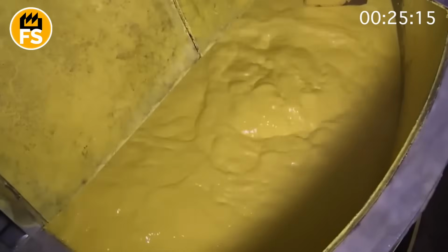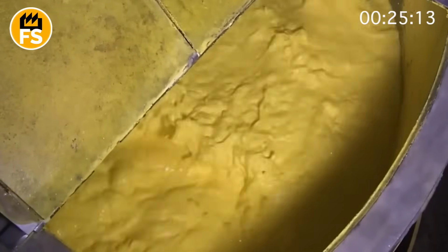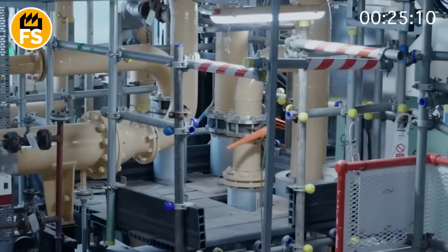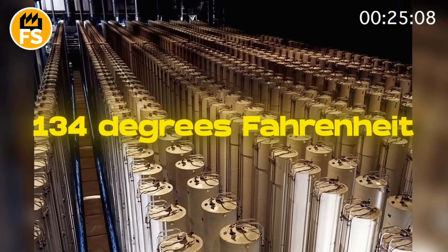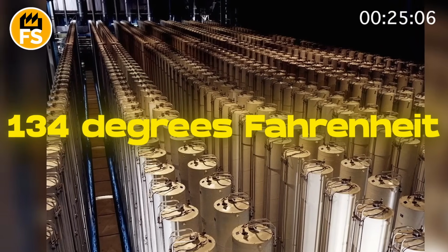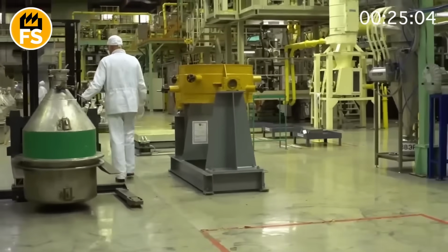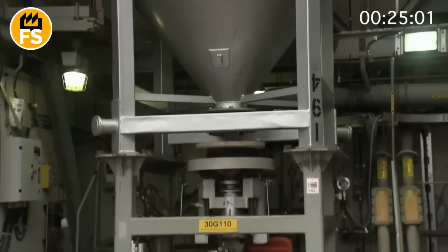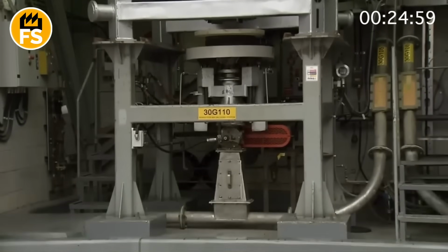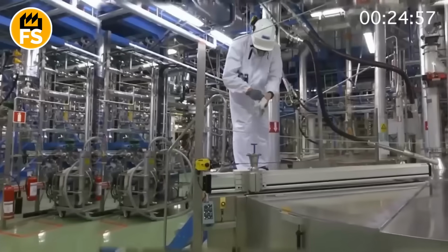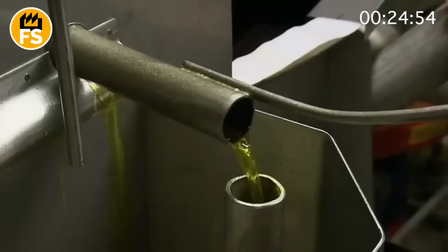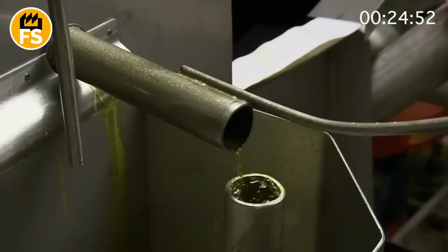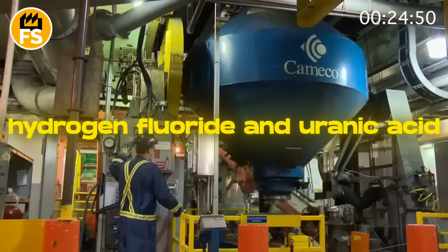Uranium dioxide is treated with fluorine in special reactors at a temperature of 1000 degrees Fahrenheit. And as a result of the reaction, a volatile, transparent gas is formed, which boils at 134 degrees Fahrenheit. That is, you just need to heat it a little, and it turns from crystals into vapor. But it's not that simple. It is extremely toxic. It corrodes metals, destroys skin, and in humid air, it immediately turns into hydrogen fluoride and uranyl fluoride. That is, a deadly cocktail.